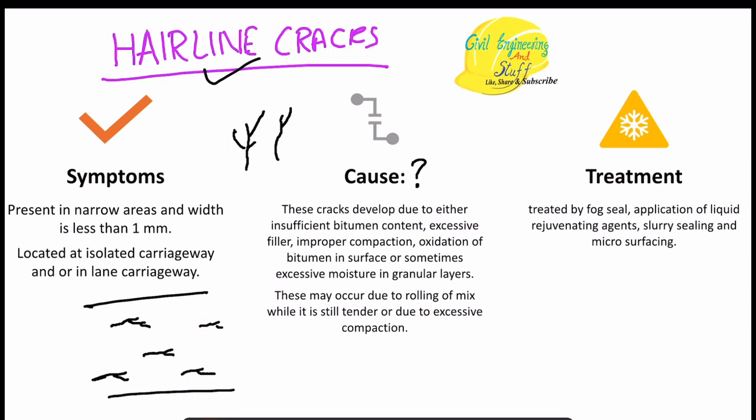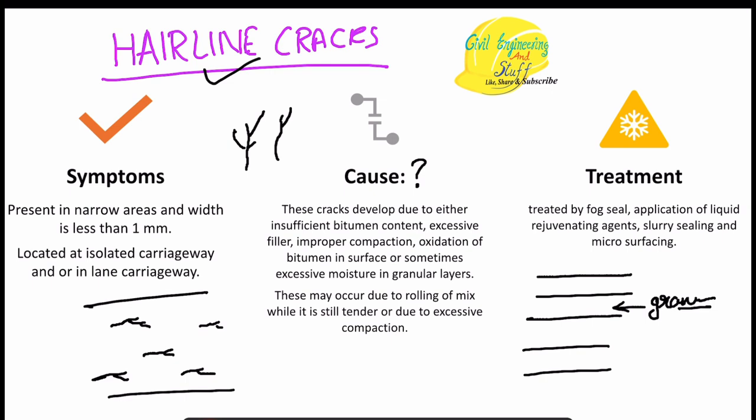And we know that flexible pavement is a multi-layered pavement system where the base course can be of granular or unbound nature. Now, because of improper drainage conditions, if this layer is affected by moisture, and this moisture propagates in the upward direction, or the moisture from the ground level, down the line, with passage of time, percolates to the top surface, that is the surface course of the flexible pavement, then these kinds of cracks may appear.